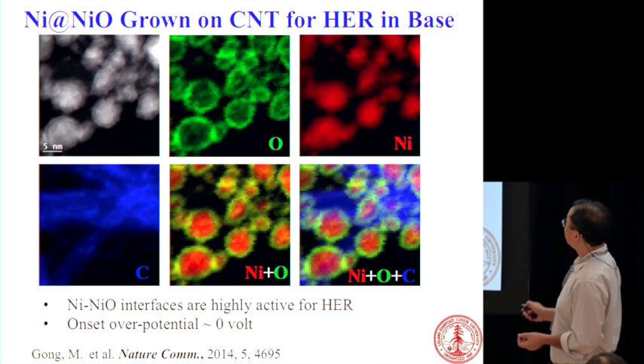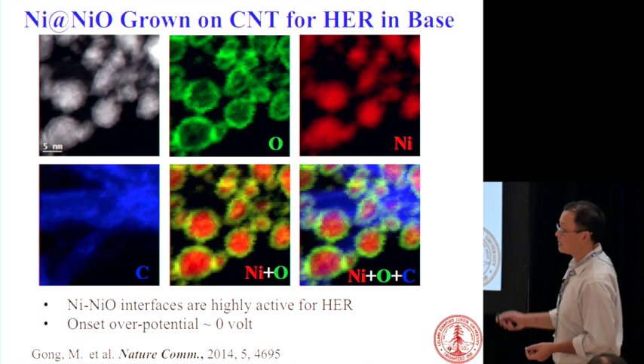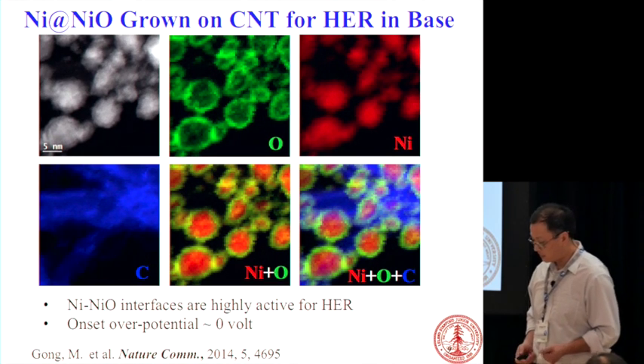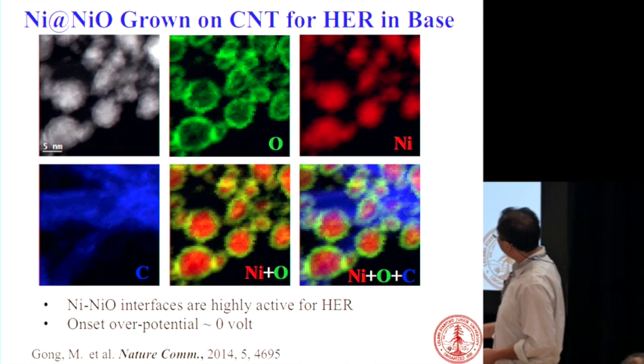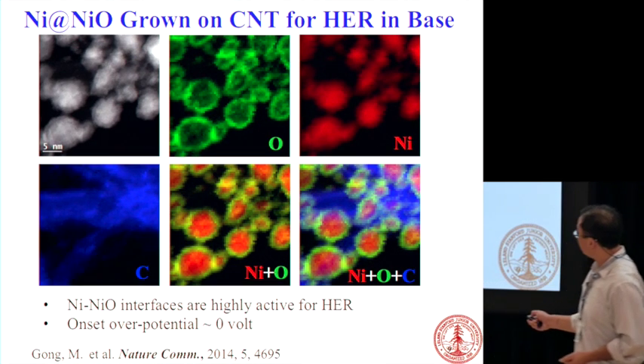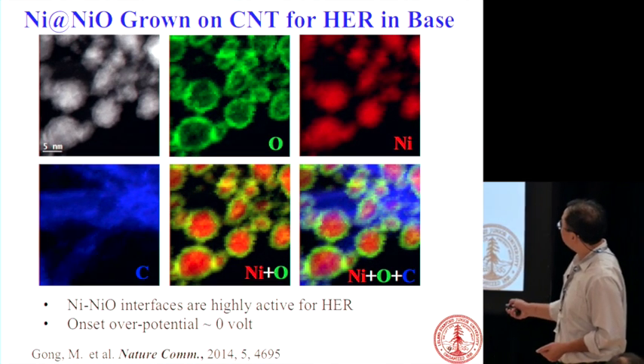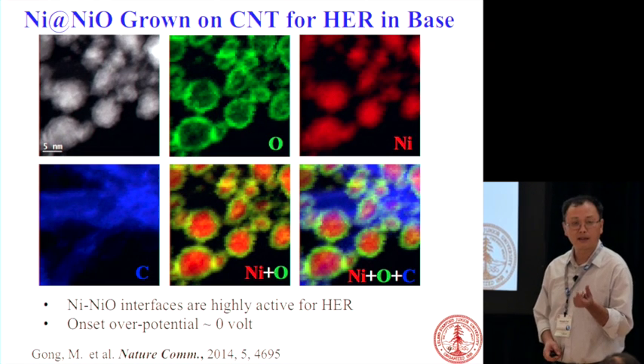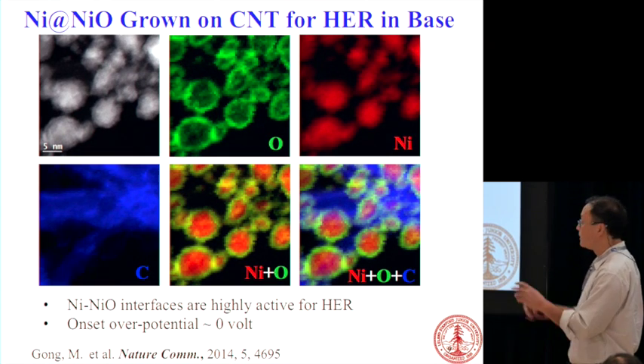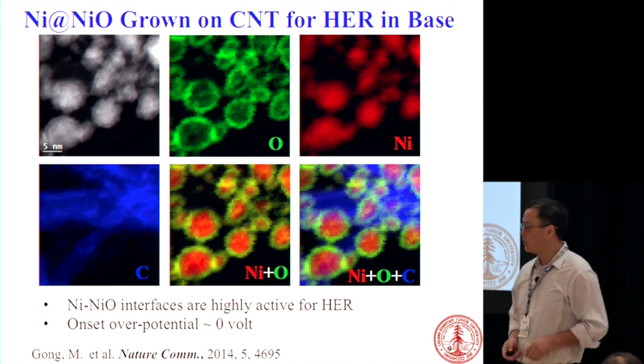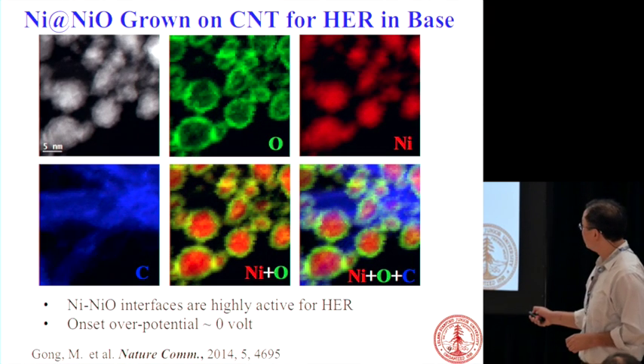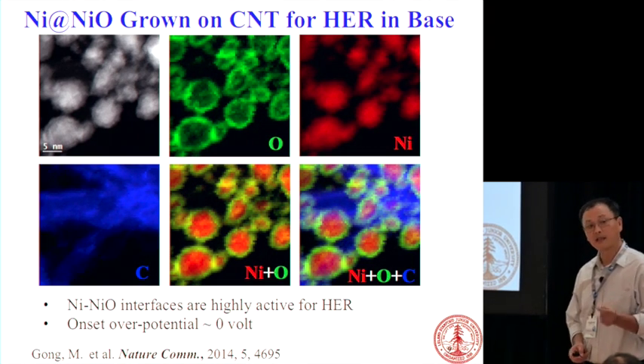So we identified a material that looks like this. It basically looks like nanoparticles, but it actually has nickel oxide. So the green part is oxidized nickel. Okay, it's like a shell on the outside. But then the middle, the red phase is actually metallic nickel.